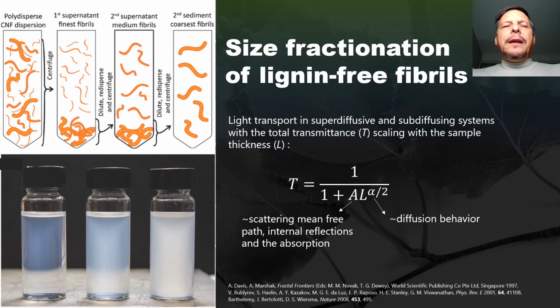And already we can see that the scattering in the aqueous suspension will be quite different depending on the fibril dimensions, thinking that these are all at the same concentration. And that, of course, has to do with light transmission, light scattering. And here we have a typical equation that looks into the effect of, for instance, the scattering mean free path and diffusion behavior of the material. Not only in suspension, but when they are forming a network such as paper. And this reminds us of other theories that are very typical to paper makers, such as the Kubelka-Munk theory of light absorption and light scattering.